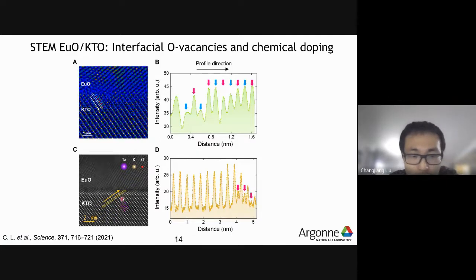And then using the dark field image, which is sensitive to the heavy atoms, following this arrow, near the end of this arrow here, the right side, which corresponds to the interfacial region, we found some additional peak in between tantalum sites. So this means the original potassium site is replaced by europium, which means there is an interfacial doping effect. We think both of these oxygen vacancies and europium doping can contribute to the formation of excess charge carriers that is responsible for the conducting interface.